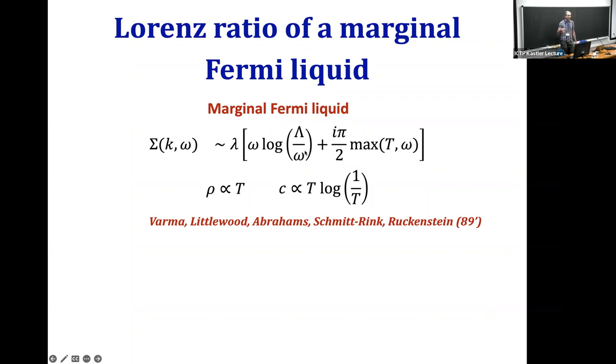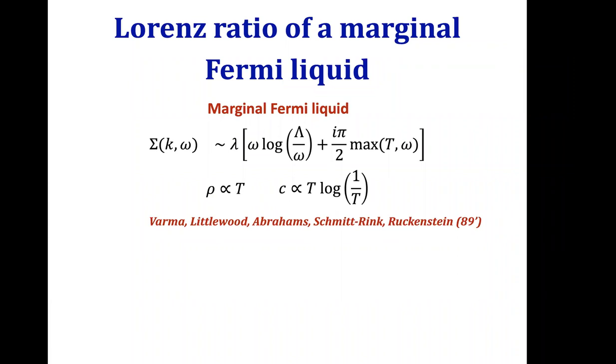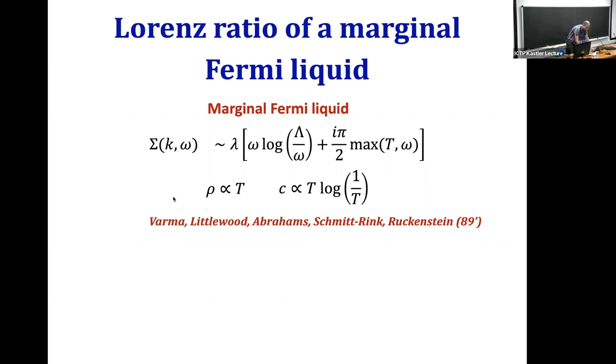The real part has a logarithmic correction to the usual Fermi liquid behavior. Lambda here is some coupling constant, and the imaginary part scales like the maximum of T and omega. This implies in particular that the single particle scattering rate at zero frequency scales like temperature. And in some situations, if this scattering of single particles is large angle scattering, Umklapp scattering, that also implies that the resistivity scales linearly with temperature. And the specific heat would get this logarithmic behavior. Both of these behaviors are actually seen at this magic doping in the cuprates.